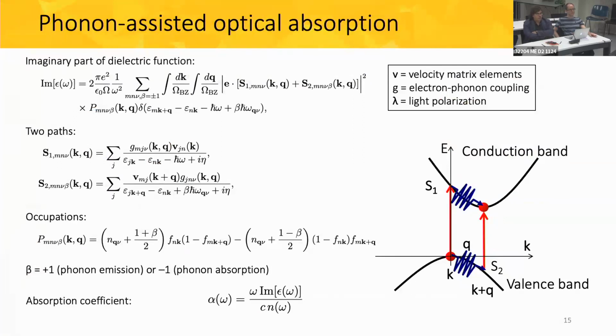Very great question. Yeah. So for the case of silicon, we're lucky that we know that the GW and LDA wave functions are very similar to each other. Indeed, in cases where there's a very large change in the wave function, we need to take this into account as well. In those cases, my intuition is we need to probably start with a method that's a better starting point for GW, whether it's a hybrid or a self-interaction corrected Koopmans approach, perhaps, where your starting wave function and the correct wave function are closer to each other.